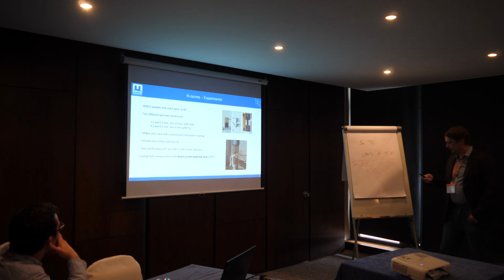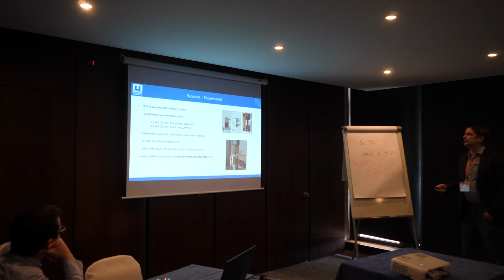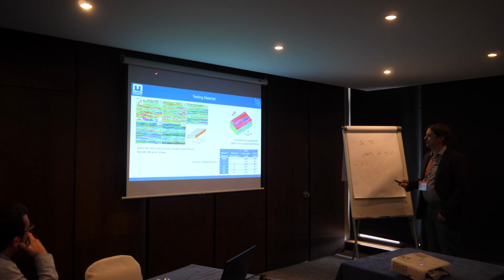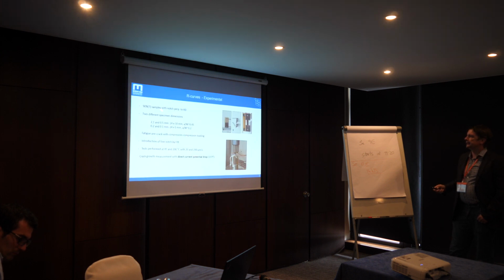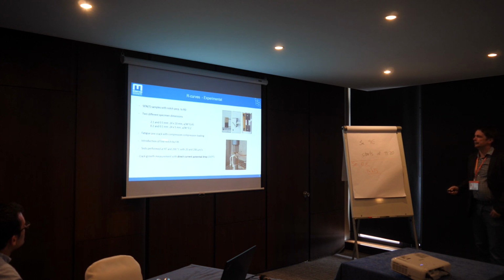The experiments were a little bit difficult. We had samples where the notch was introduced perpendicular to the rolling direction, and we were working with two different specimen dimensions. That's the unfortunate thing for reasons of comparability. We had to do this due to buckling issues. We looked at different sheet thicknesses, from 2 mm down to 0.1 mm, and for the thicker sheets, the fatigue pre-crack was introduced by compression loading, and for the very thin sheets, we had to make only a fine notch, which was only possible with a focused ion beam station.